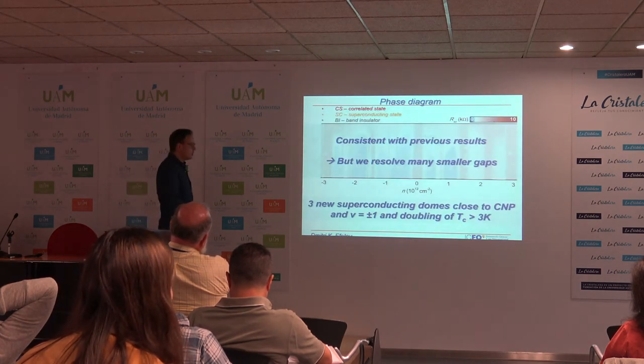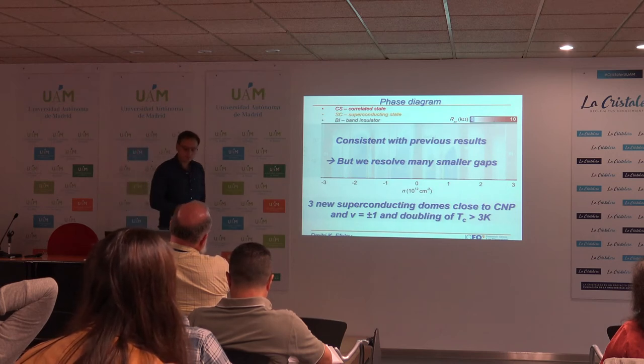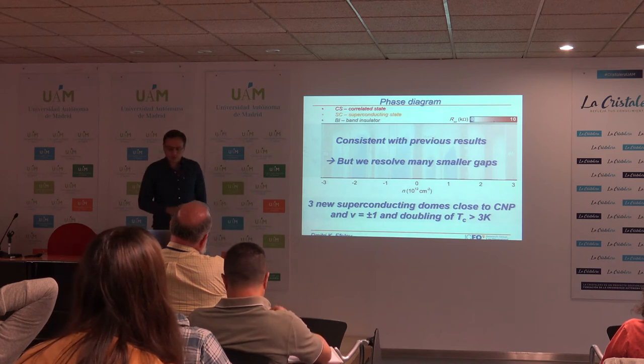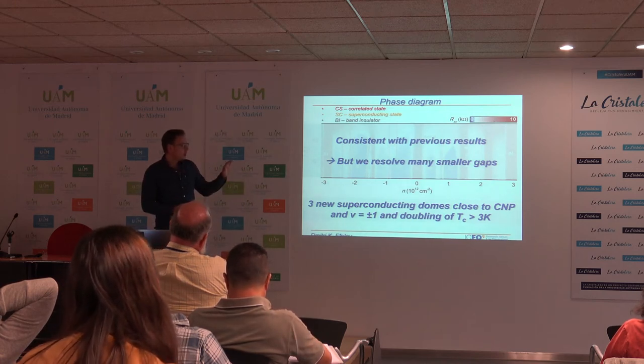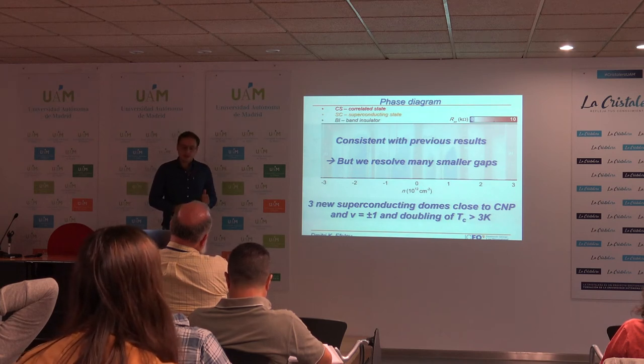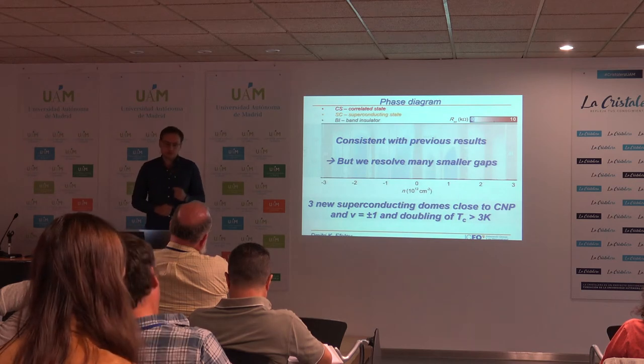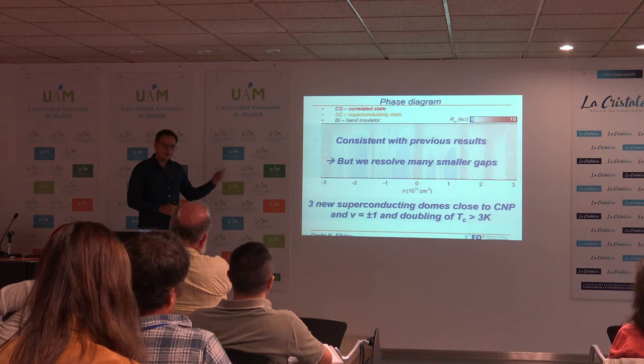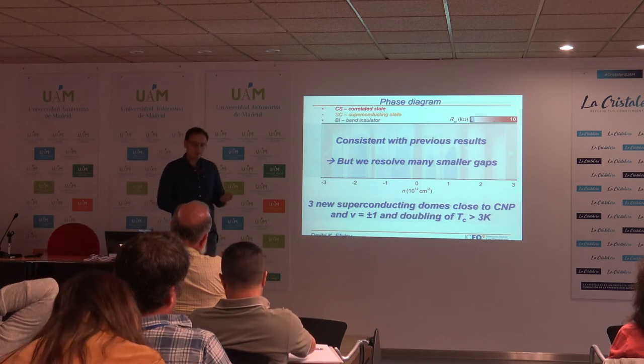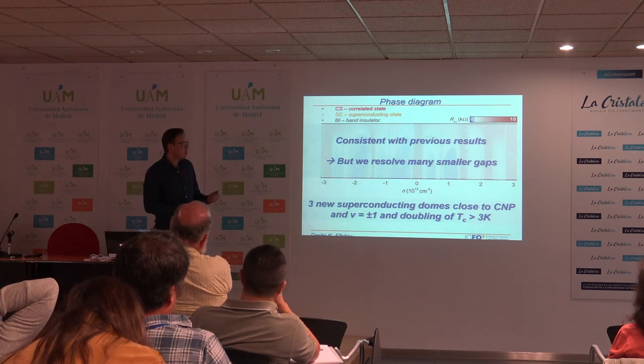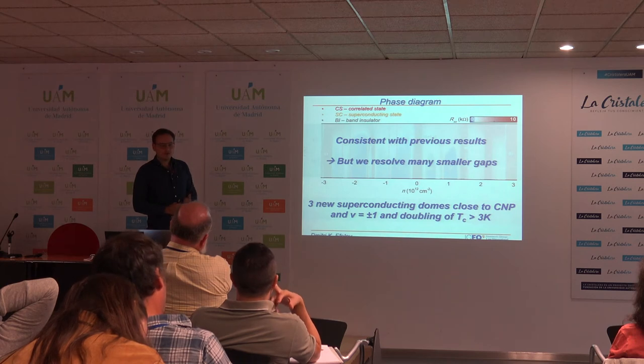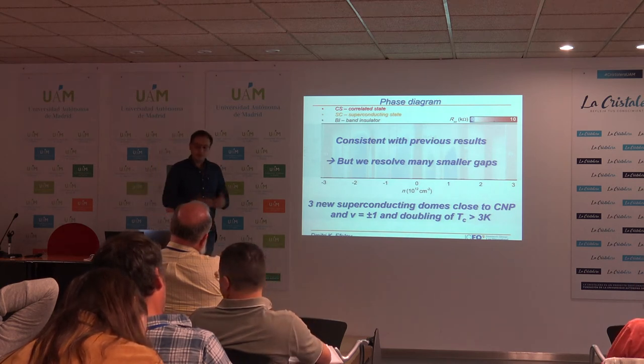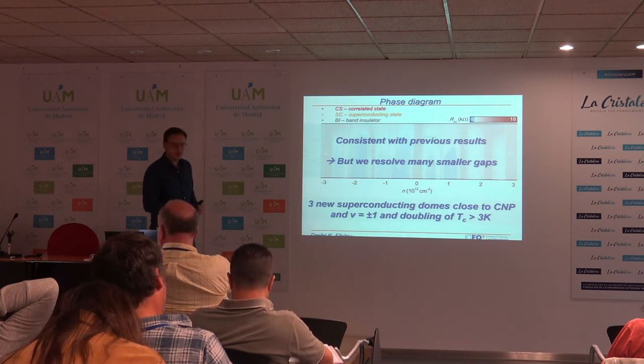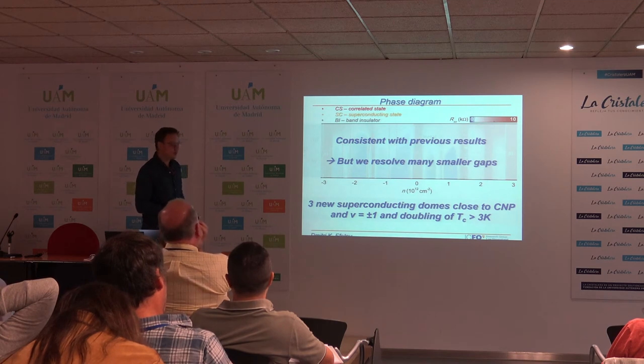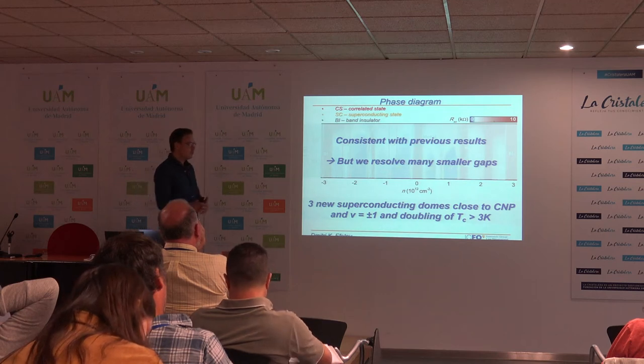So these results, in principle, are consistent, I think, with the results of Pablo and from the Columbia group. In principle, really all of the gaps which we are extracting from the insulators are indeed the strongest for the -2 and +2 states. However, we think because we have cleaner devices, we now observe other gaps which are much smaller. So for example, the gaps at quarter filling or three-quarter filling are several times smaller than the gaps at half filling, but probably they were not resolved in the previous results because just disorder in these inhomogeneous devices can easily kill such small gaps.